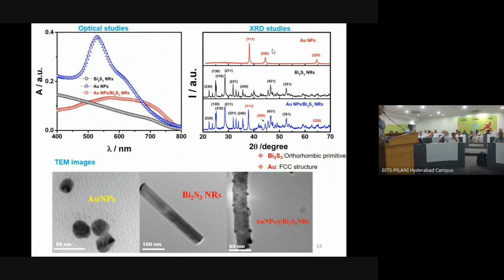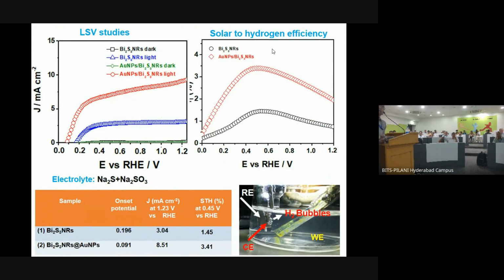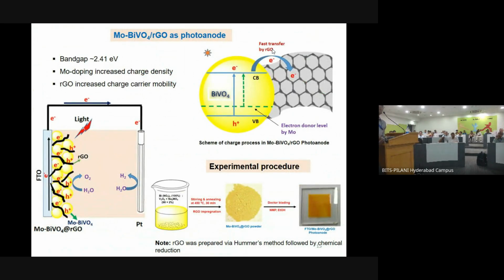Then you can think about it, like this is the optical study, and you have the X-ray study, and you can look at the way the rod has grown. On that you have a tiny particle which is roughly around 15 to 20 nanometers. So this is where you can decorate it. That means you can confirm each one, and then you can look at the efficiency, and the conversion efficiency typically goes up to, say for example, 4 to 5 percent.